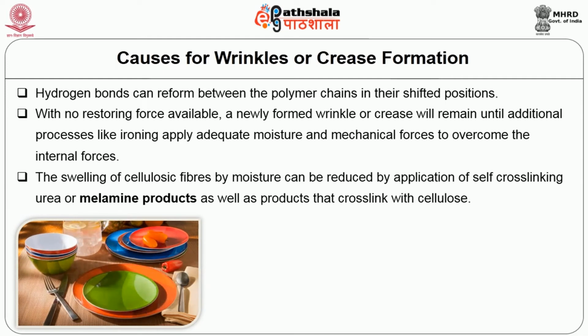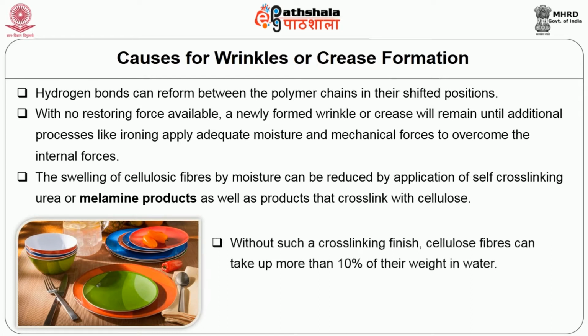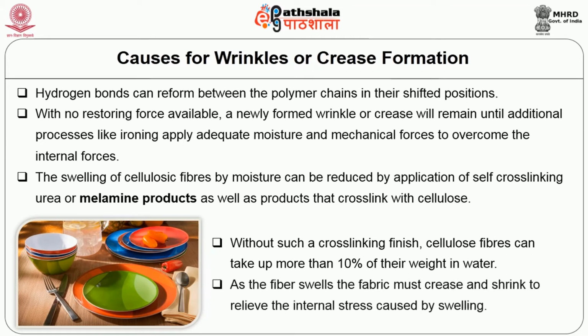The swelling of cellulosic fibers by moisture can be reduced by application of self-cross-linking urea or melamine products, as well as products that cross-link with cellulose. Without such a cross-linking finish, cellulosic fibers can take up more than 10% of their weight in water. As the fiber swells, the fabric must crease and shrink to relieve the internal stress caused by swelling.